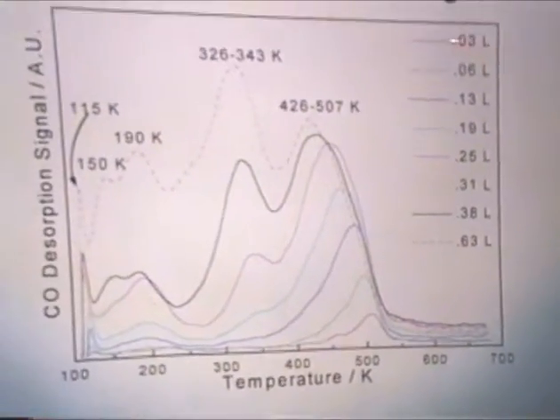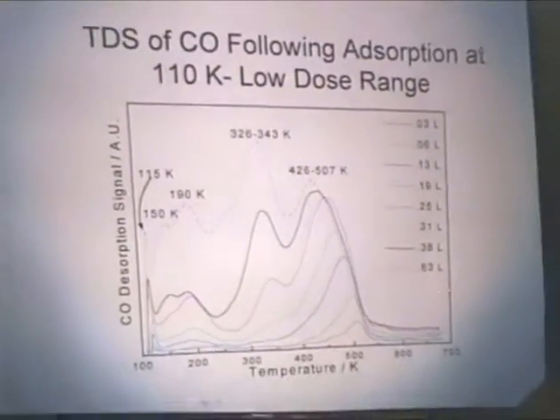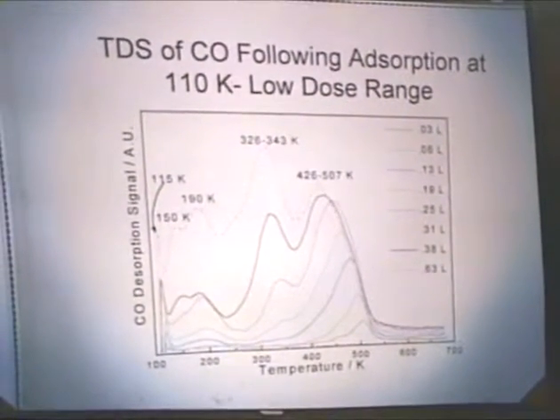This covers a range of 1/32 of a Langmuir to 5/8 of a Langmuir, where Langmuir is a measure of exposure, which is equivalent to 1 times 10 to the minus 6 torr times seconds. And you see that as we get to the higher and higher doses, we begin populating a total of 5 states, two states above room temperature and 3 states that come off below room temperature.